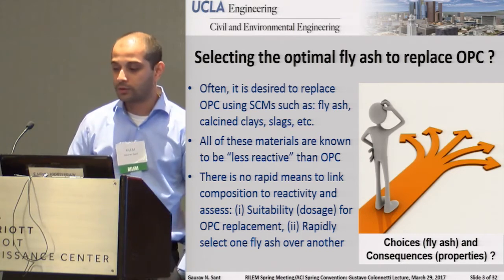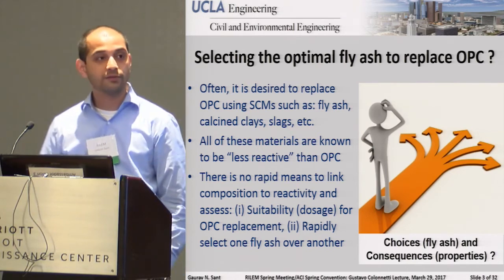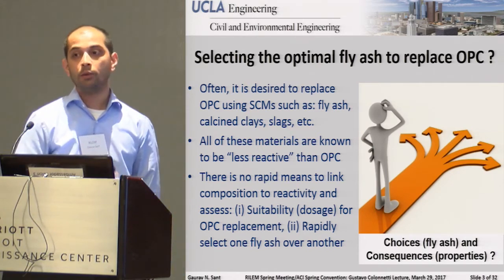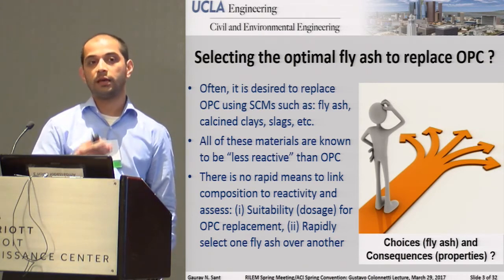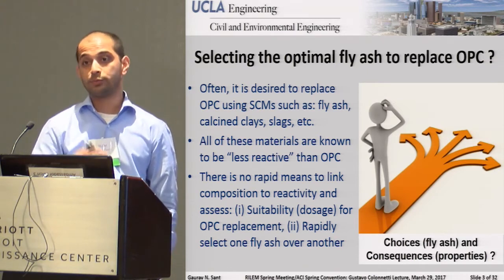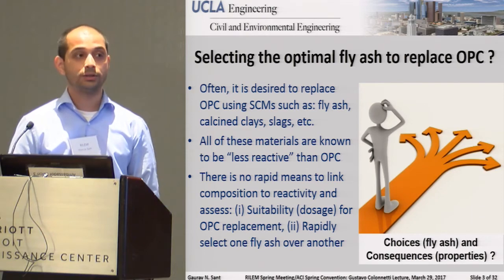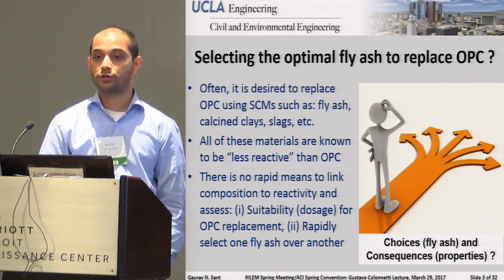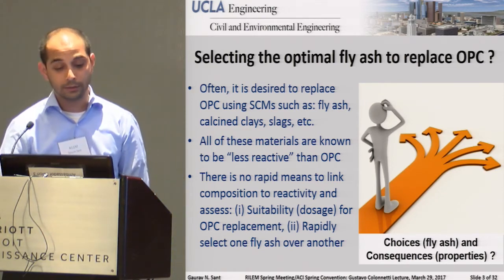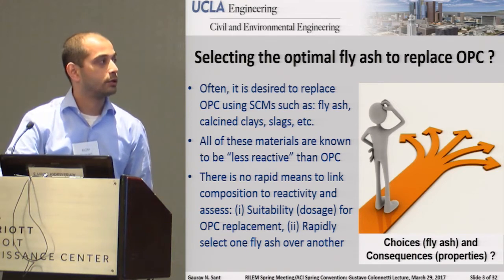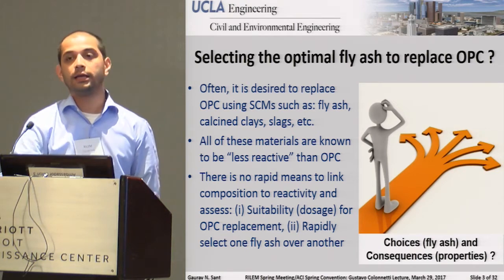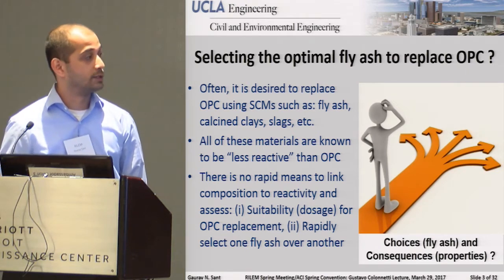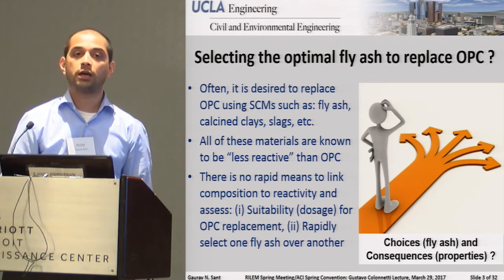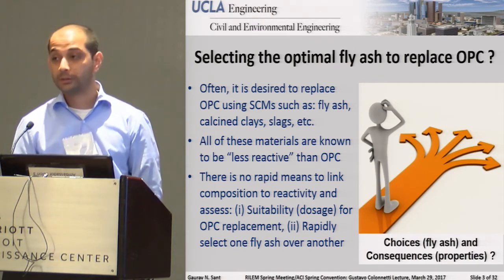Very often this is considered in the context of, oh, they've got an amorphous phase, they've got a crystalline phase, et cetera, but we don't really have a good means to take fly ash A and fly ash B, which might, for example, both be low calcium ashes, and say, just based upon composition and structure, which one is more reactive than the other. So really the first question that comes about is, how do you ascertain the dosage and the suitability for OPC replacement? And how do you start to discriminate different fly ashes from each other?